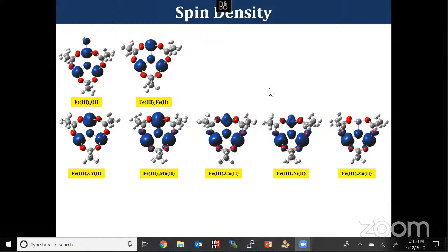So here you can see the spin density pictures of the corresponding cluster models that we modeled with various first row transition metals. The reason why I have shared this picture is that before doing grand canonical Monte Carlo simulation to get the isotherm graph, we want to know what happens when we replace with different metal atoms. When we change the metal atom, the charge and spin density change. So we want to know whether it plays any key role in the interaction energy of the gas molecule.